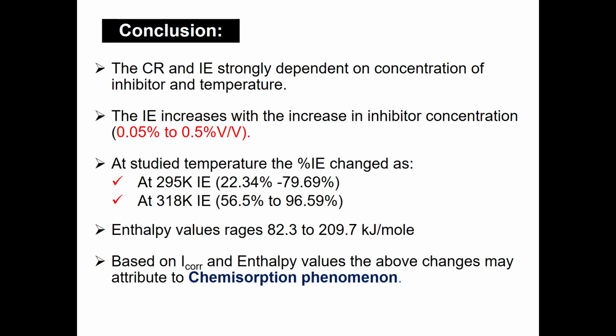And as a conclusion, we can say that the corrosion rate and inhibition efficiency are strongly dependent on the concentration of the inhibitor and the temperature. The inhibition efficiency increases with the increase in the inhibitor concentration. At temperatures 295 and 318, the percentage of the inhibition efficiency increases, and enthalpy was 82.3 to 209.7 kilojoule per mole. Based on that, we can say that it is a chemisorption phenomenon.